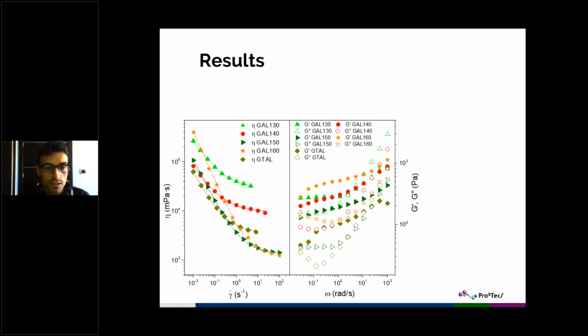behavior. Why? First of all, we are obtaining really high viscoelastic function that was not expected. We are obtaining really high relative elasticity, that we were in fact expecting. In fact, the crossover is shifted to high wave number, even within the frequency range that we cannot see any crossover. And the shear thinning behavior is the sharpest one of all of them.